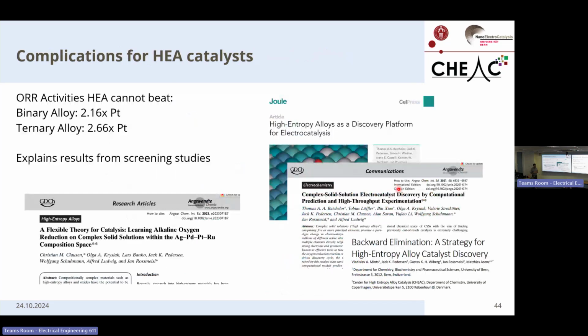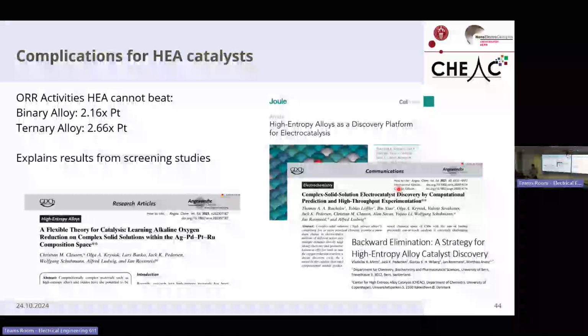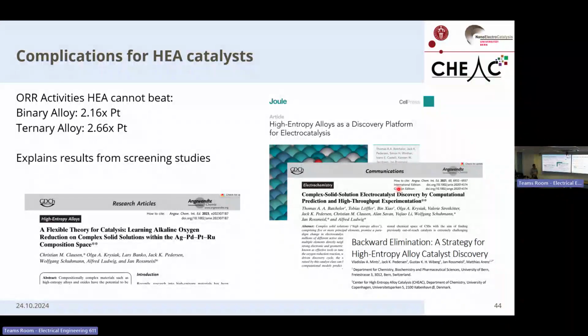We can also calculate which binary and ternary alloys high entropy alloys will not be able to outcompete, simply because of lack of surface. So if you find a binary alloy that doubles the activity of platinum, a high entropy alloy cannot outperform it anymore. And that probably explains why within our screening studies, all screenings end up in these binary and ternary catalysts.